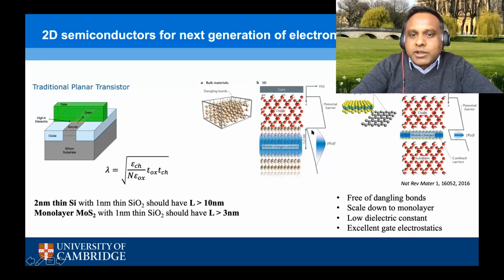When you go from a 3D semiconductor to something that is sub 1 nanometer in thickness, then the probability distribution of the carriers is confined within the 7 angstrom thick semiconductor. And what this means is that the application of a gate bias influences all the charge carriers uniformly, so the device can be readily turned on and turned off. This allows you to decrease the subthreshold slope close to the theoretical limit of 60 millivolt per decade.